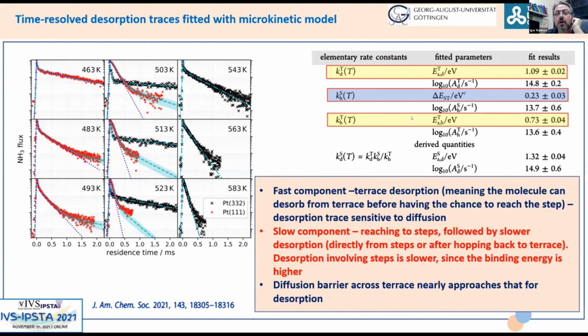eV. What is actually quite remarkable here, and this is, by the way, the reason why we are seeing this bi-exponential decay, is that the hopping barrier is nearly equivalent to the desorption barrier, 0.73 eV versus 1.1 eV for the case of desorption, which means the hopping is very slow. Now, moreover, what is again remarkable here is that the prefactor for desorption from the steps and the prefactor for desorption from terraces are nearly identical.